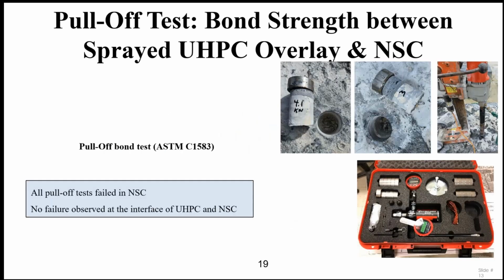We've done quite a bit of testing with the direct pull-off test. So another way, we have sprayed. We've done lots of tests. These are some of the old pictures, actually. We have sprayed the UHPC, and then did a direct tension test, basically following ASTM C1583. I can tell you that we've never seen the failure take place at the interface between the normal strength concrete and what was sprayed. It's always at the normal strength concrete level. And the same results for cast in place have been reported by people like Ben Graybill at FHWA and others. So that's very good news.